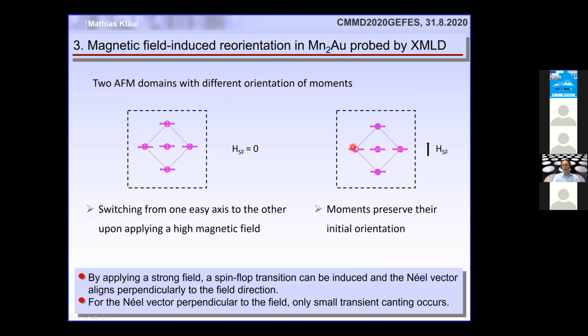And if you apply an even stronger field, then they will still stay in a direction that is perpendicular to the applied field and just cant a little bit. And so this is something we wanted to check. For this, we use manganese two gold.